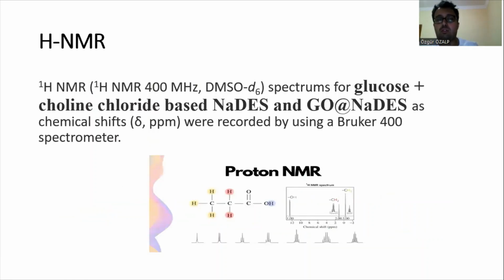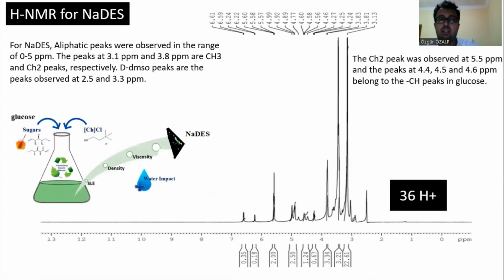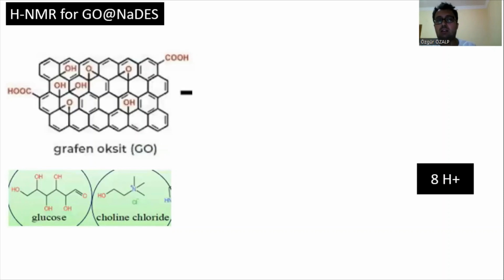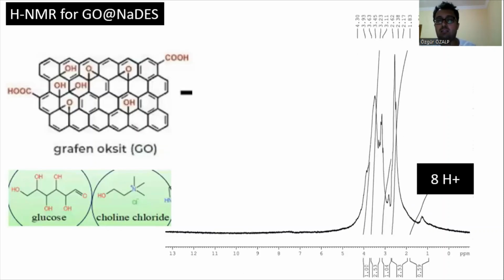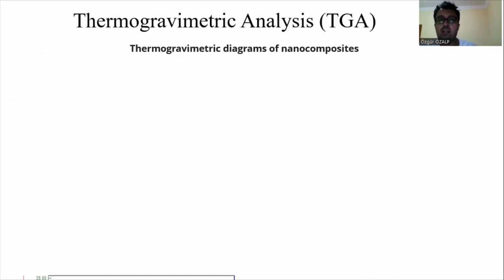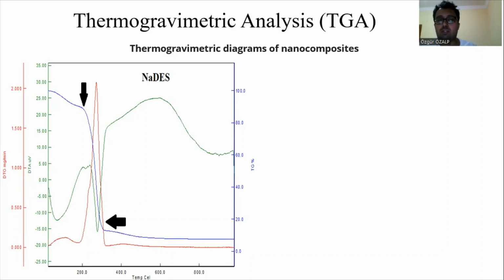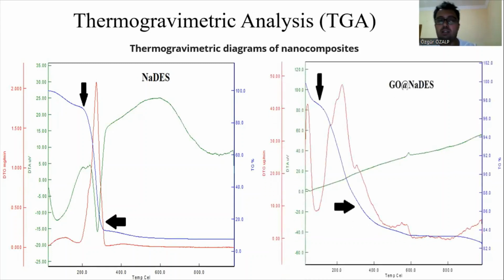Third is proton NMR. For choline chloride, glucose and water, 36 hydrogens are observed. After combining with graphene oxide, different types of hydrogen are removed and the combination is very successful. You can see 8 hydrogen peaks. Fourth is thermogravimetric analysis: natural deep eutectic solvents decompose after 300 centigrade, but graphene oxide still contains carbon after 1000 centigrade.